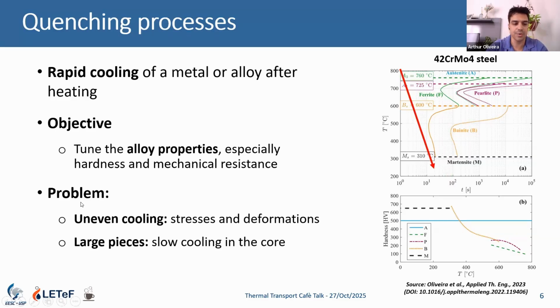And that can lead to uneven cooling, so we are talking about stresses and deformations of the final part. When it's regarding large pieces, it's easy to form martensite near the surface of the part, but in the core, because of heat diffusion, the cooling process is much slower, so there you can form other phases instead of martensite.